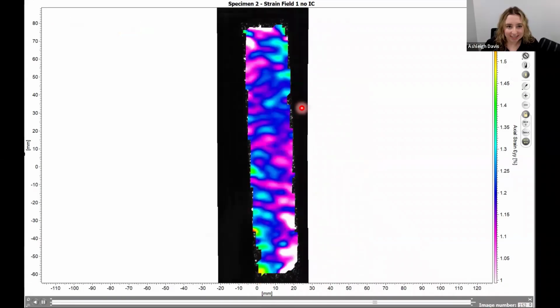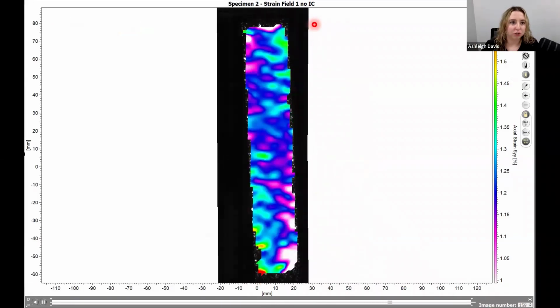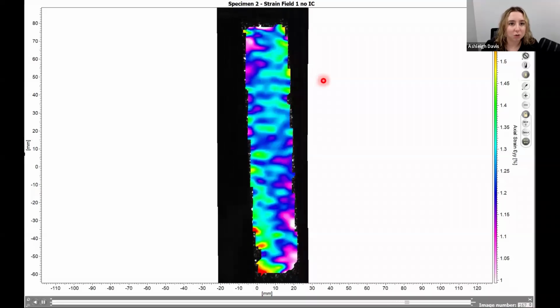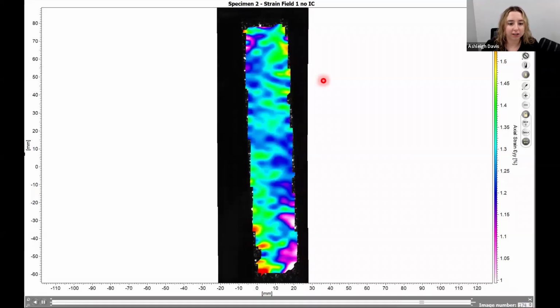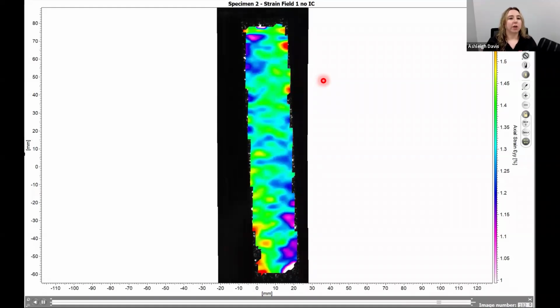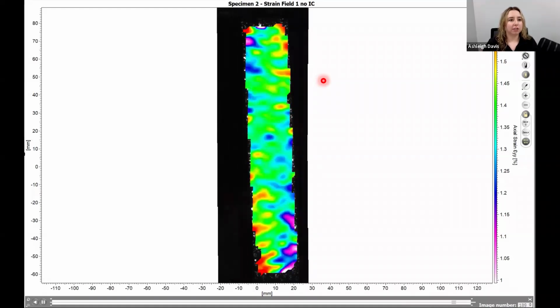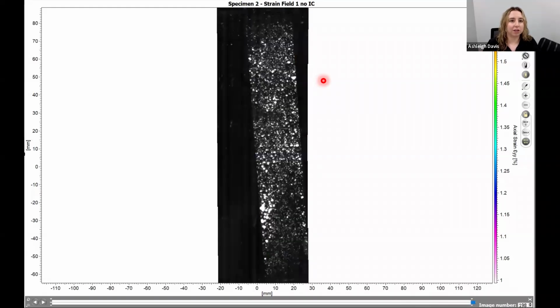So we're not getting even stress strain distribution throughout the specimen. We can see the localized stresses occurring. Ultimately, it's going to fail at that lower jaw face, which is not an appropriate break. And this would be a failed kind of break. With something as simple as the specimen stops, we can hope to avoid this kind of failure.